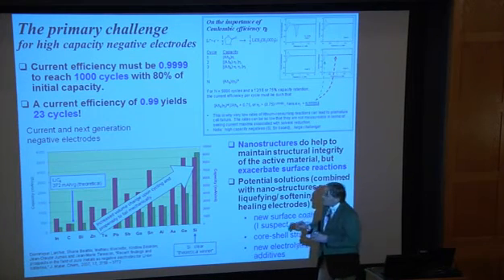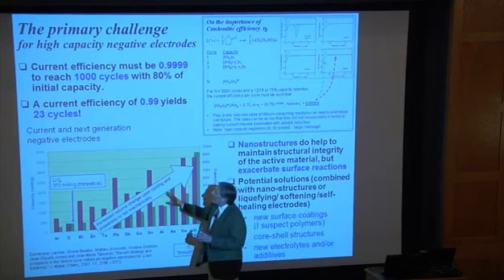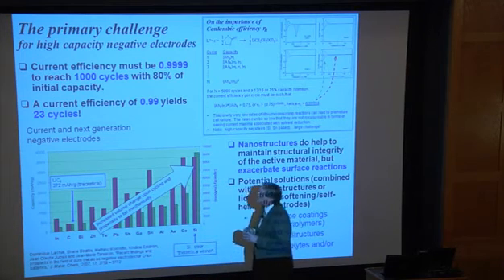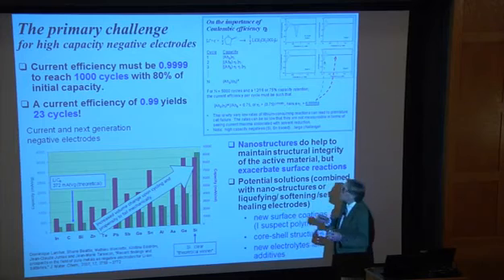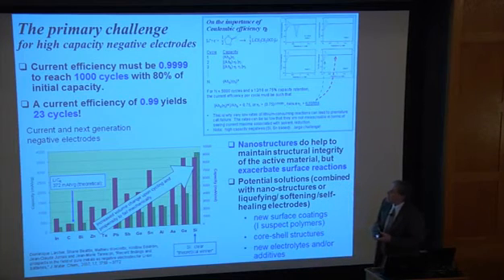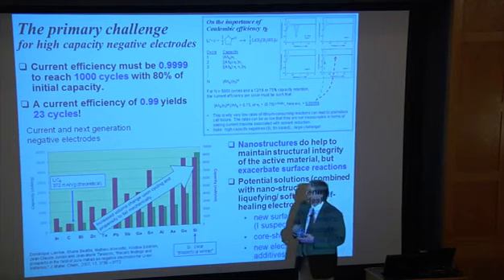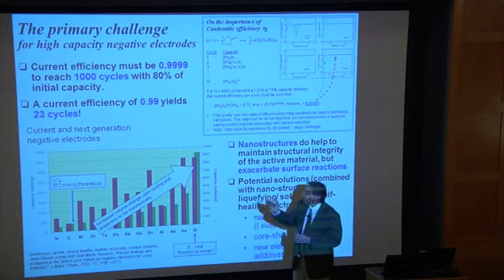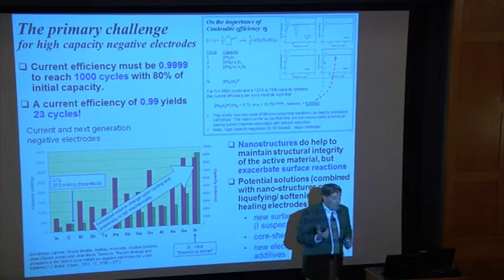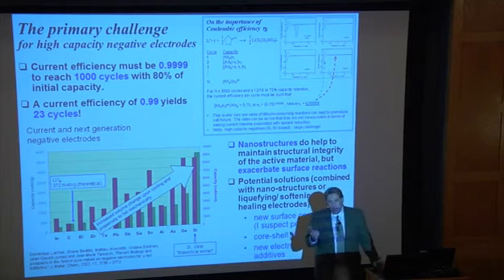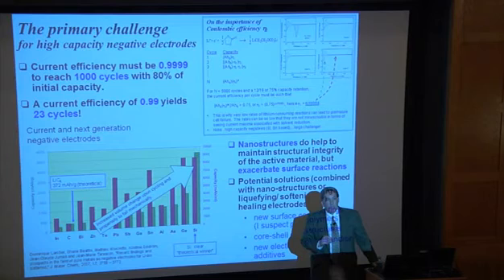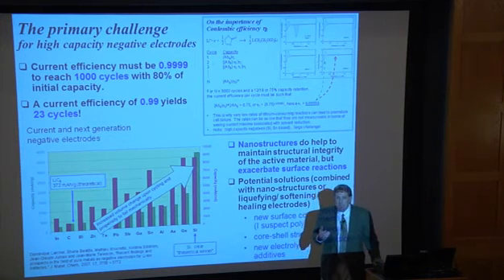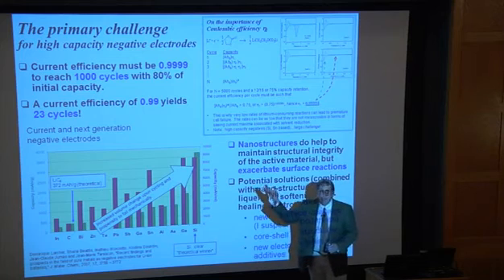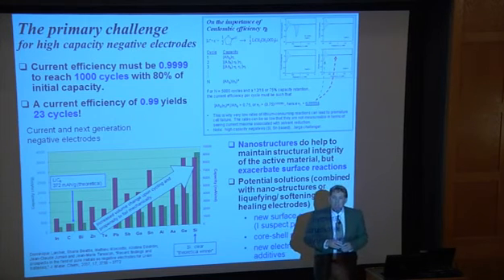So what I would say is, this is a figure I showed earlier, and I mentioned that if you look at the effect of a constant current efficiency, you need a value of about 4 nines to get 1,000 cycles, and it turns out if your current efficiency is about 99%, you'll get about 23 cycles. The reason this is important is a lot of researchers will publish work on silicon. They'll say, well, the current efficiency is pretty high, it's about 99%. Well, that's not good enough for these systems, because 99% is not going to get you anywhere near what you need for an actual application.